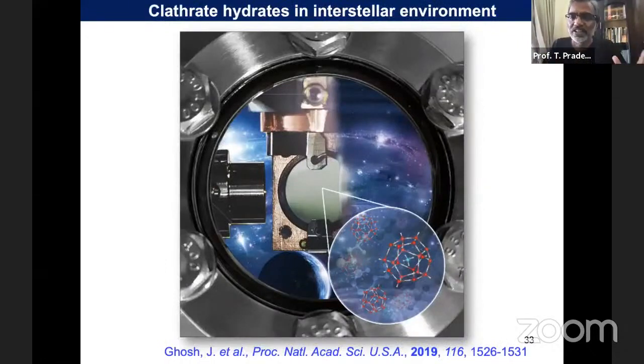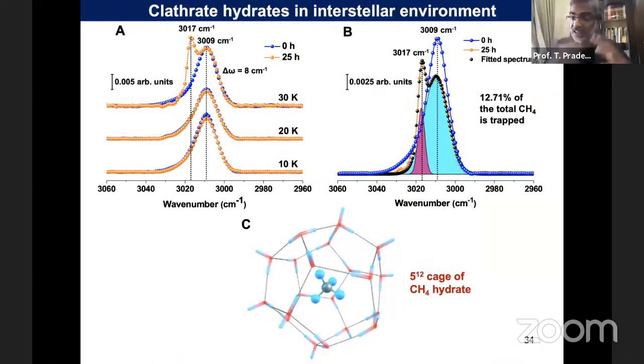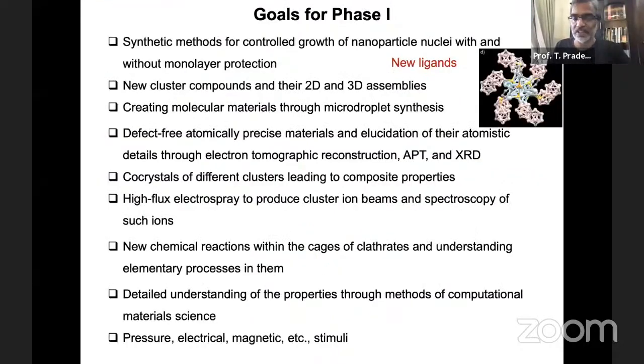What we studied, or what we saw, was that in a vacuum chamber, you can simulate conditions similar to space. And in that condition, at 10 Kelvin and in ultra-high vacuum, you can create gas hydrates. And we published that. So what that means is that the molecule inside these cages can possibly do interesting science. And this science, or this chemistry, this physics, can be probed with spectroscopy. And this is one of the motivations of the study.